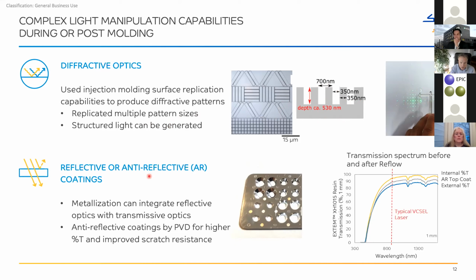Something that works very well is putting a coating on top of our material, whether it's reflective or anti-reflective. Like I said, sometimes you want to have a mirror element in your connector, because the VCSEL, of course, gives you a vertical light that you want to bend 90 degrees into the die. Extem and Ultem are very easy to metallize. You don't need a primer, so you can directly metallize it and get very good adhesion. And I already mentioned that you can also apply an anti-reflective coating to increase the transmission.